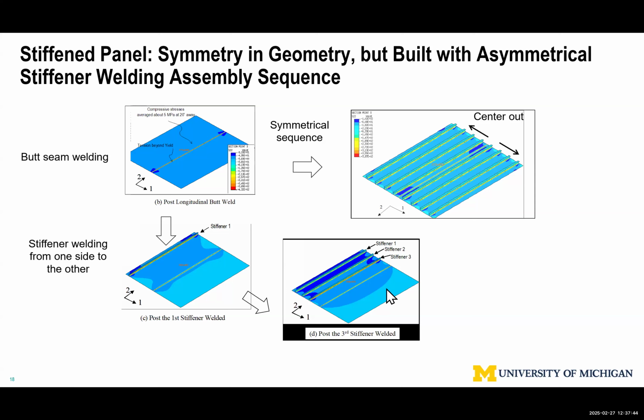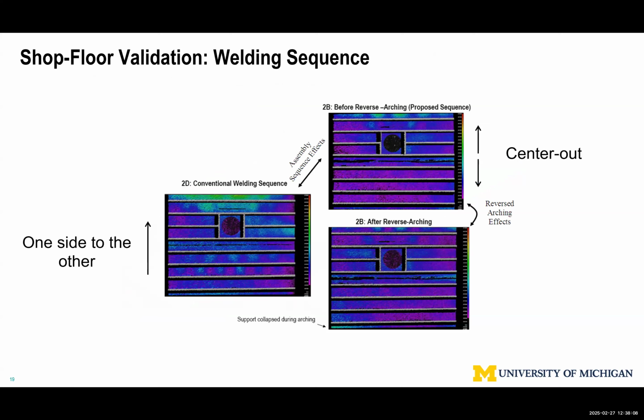Stiffener 1, stiffener 2, you can see the blue color is compressive residual stress getting built up unsymmetrically with respect to the neutral axis of the panel. If you do center out, 1, 2, 3, 4, 5, 6, 7, 8, you get about 3 times the buckling resistance versus the conventional procedure. Again, we demonstrate that with the actual production line by designing what we call a test panel that's a 16 by 20 feet size, using the conventional method, one side to the other, almost virtually nothing, right?